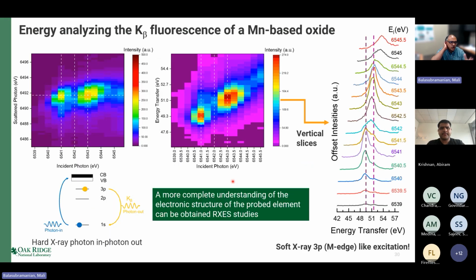So I showed you a way of doing this spin selective XES, but a more complete way of doing it is to actually do this 2D plane, where you measure as a function of incident energy, you measure the emitted energy, and generate this 2D plane. So you go to an incident energy, scan the analyzer crystal, and monitor the intensity for these various emission energies. Then you step the monochromator, go to a different incident energy, and repeat the process. By repeating this, you can get this 2D plane, which is sometimes called the resonant X-ray emission plane or the resonant inelastic X-ray scattering plane.